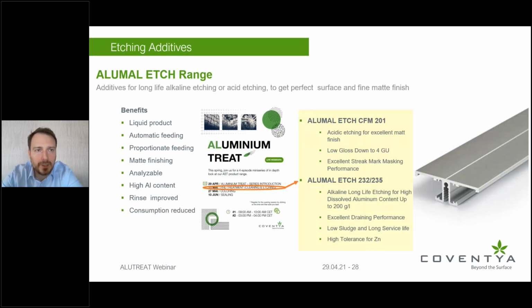Okay, the other alternative prior to the anodizing, in order to get a matte finish, was obviously etching. And we have two big families of etching. One of them is the acidic etching. Well, we are calling it acidic etching, but the abbreviation, CFM, actually stands for caustic free matte. And the pH of the bath is not very acidic.